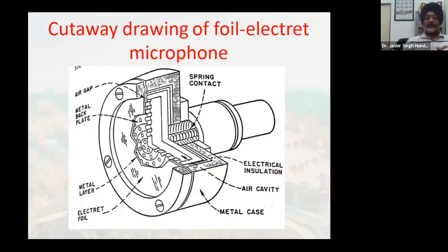Now coming to the applications of these films. They have a huge number of applications. I'll just elaborate one. In our lab at Roorkee, we were able to make a microphone in the lab itself. Though this picture is not of that microphone, we were able to prepare it. Here you can see a polymer film. We have a substrate, and there is an air gap between the polymer film and the lower electrode. So you have an upper electrode, a lower electrode, and a small air gap between those two electrodes.